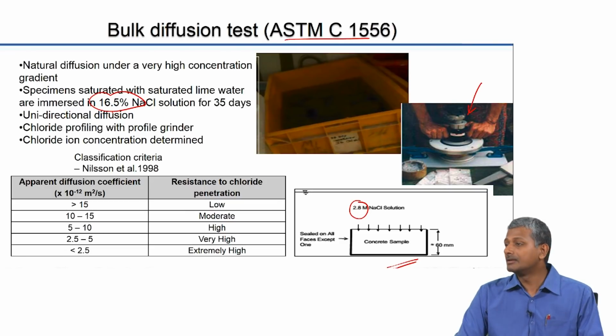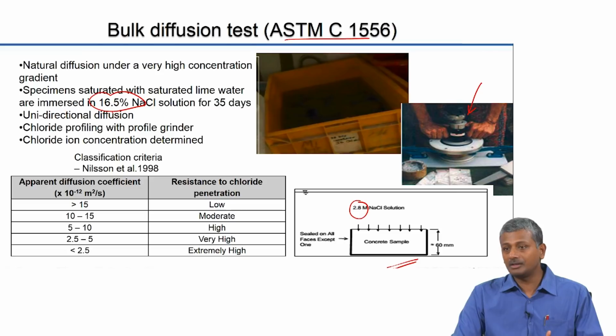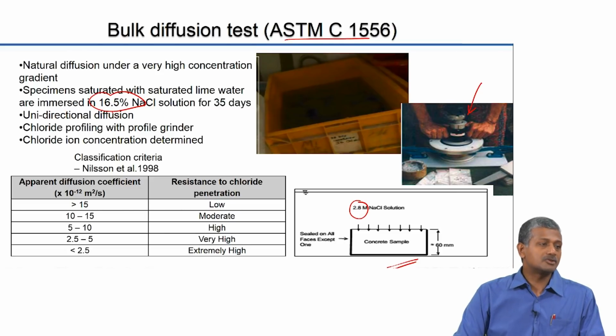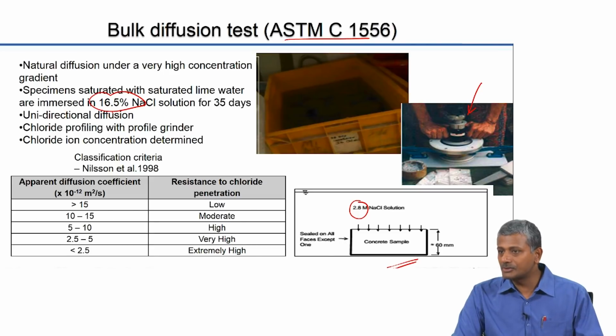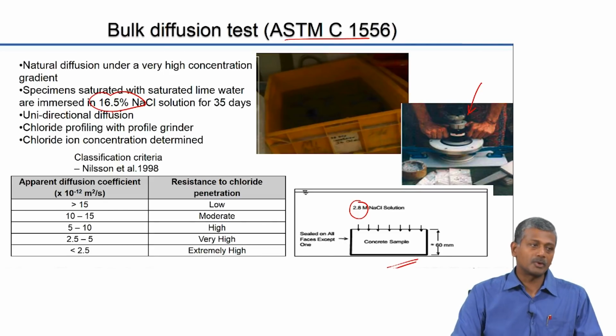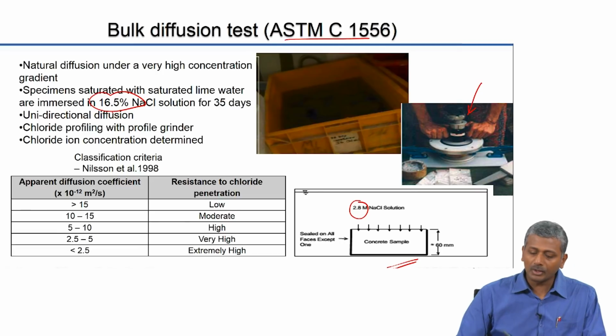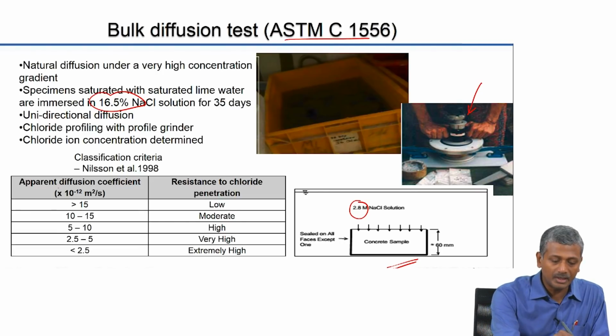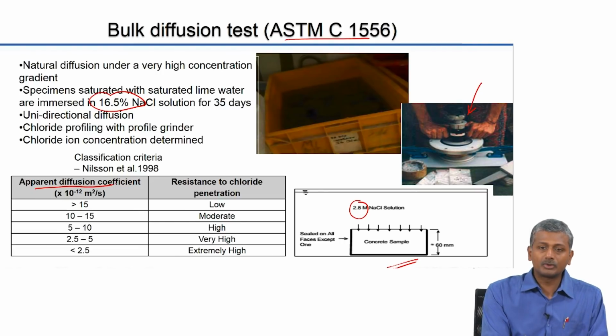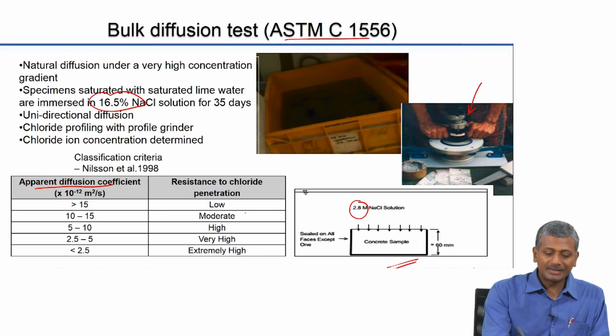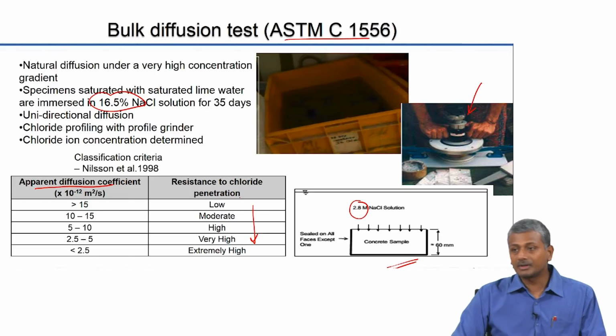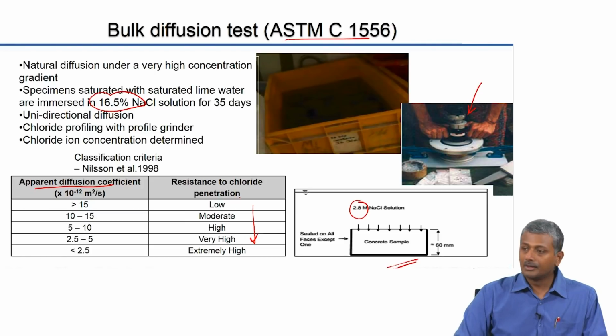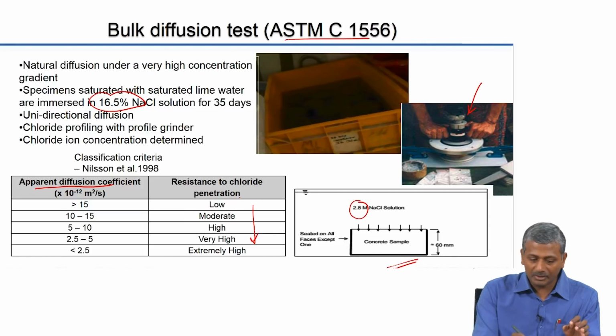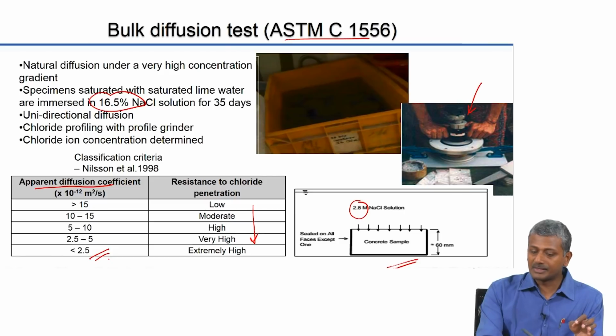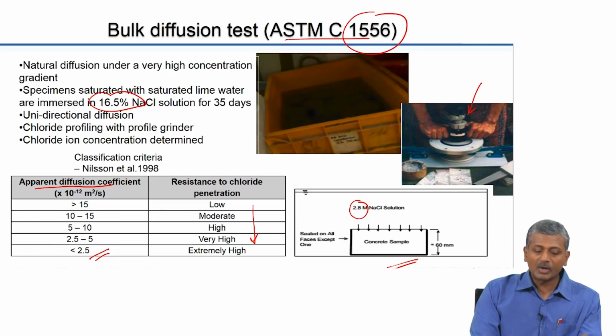Okay, so that's a very aggressive, very concentrated solution of sodium chloride. Okay, so of course we want to accelerate the test, so we use a very high concentration of sodium chloride in this case. And based on the diffusion coefficient value D that you get, the apparent diffusion coefficient values, there is a qualitative classification given for the resistance to chloride penetration. This is not standardized, okay. I mean, these values are not standardized. The test is standardized, but these values are not standardized.